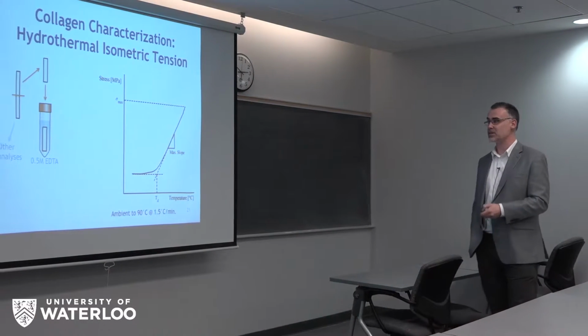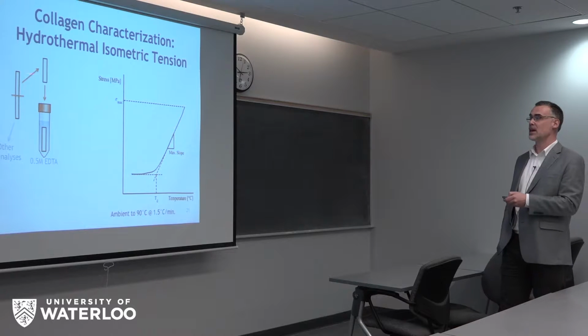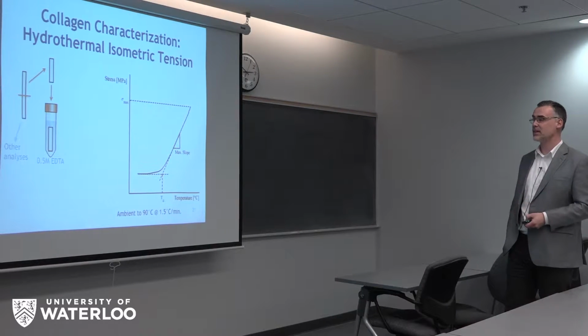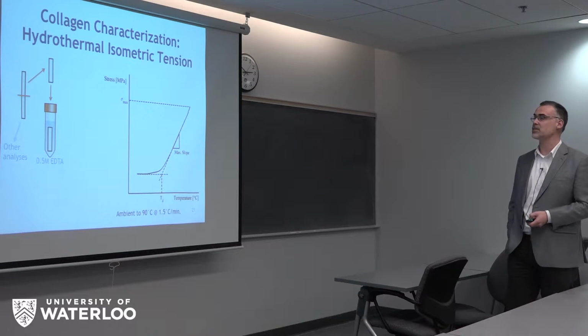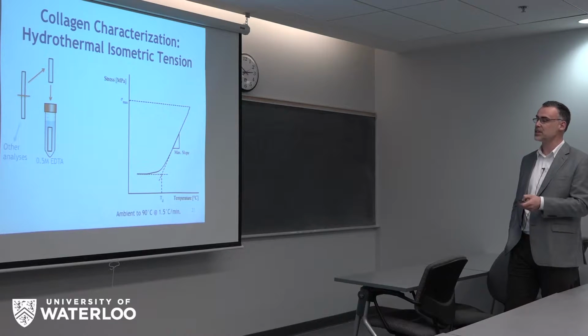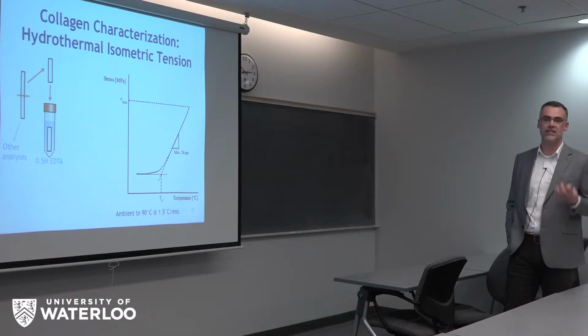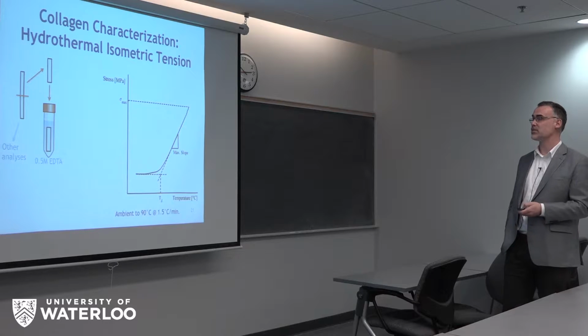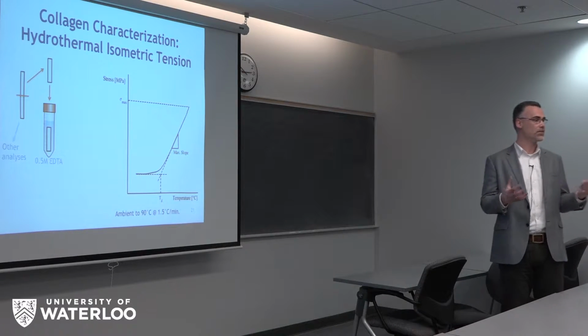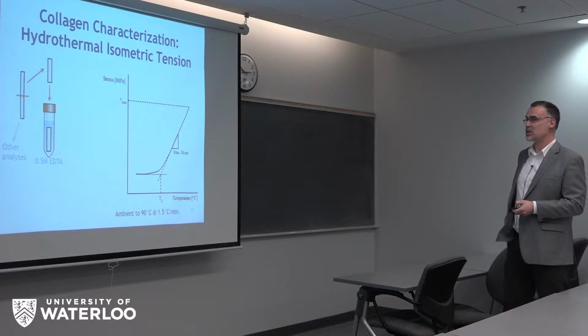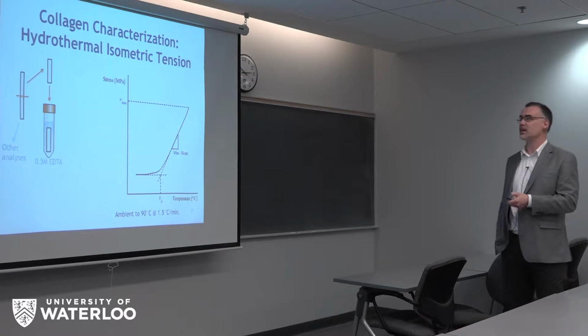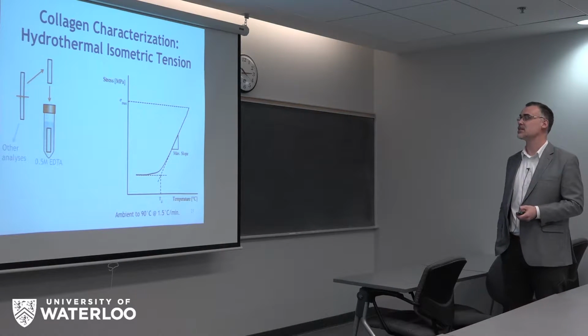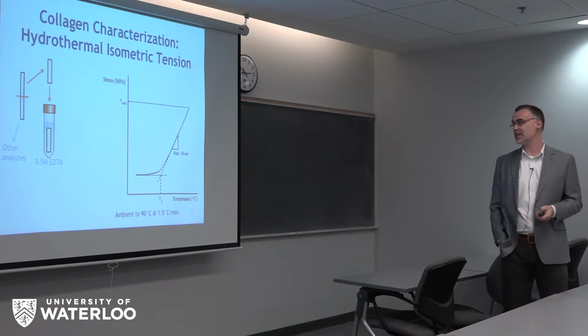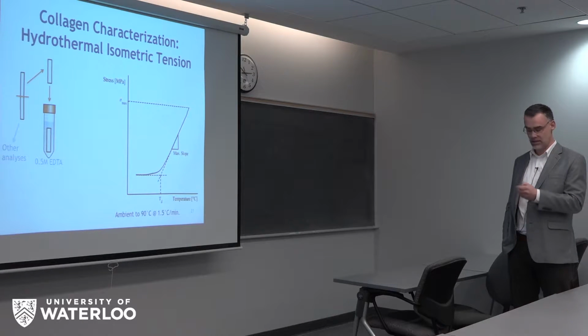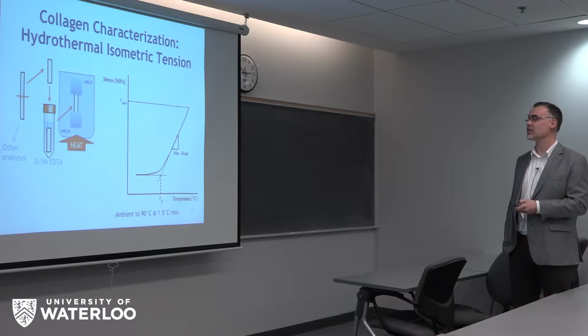And after that, we took the 2 halves of the beam, and 1 half was gently decalcified in sodium EDTA solution, and that just gently chelates out the mineral phase, and you're left with a strip of decalcified bone collagen. And then we use a thermomechanical technique called hydrothermal isometric tension testing to get a measure of thermal stability and connectivity of that network.